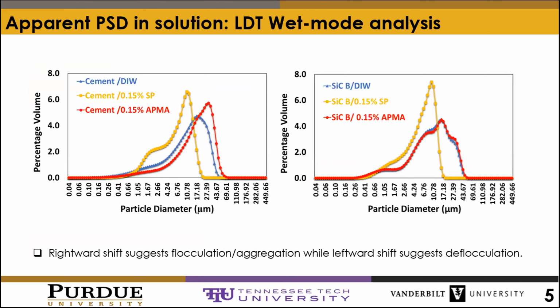So shown here is the effect of organic dispersing agents on the apparent particle size distribution. The addition of both organic species altered the apparent size distribution when compared to the apparent distribution in deionized water. Superplasticizer clearly disperses both solids, and it breaks up floc when you compare the blue and the golden curves. Whereas ammonium polymethacrylate tends to apparently flocculate cement, it has no effect on the silicon carbide in low dose when you compare the red and the blue curve as well.